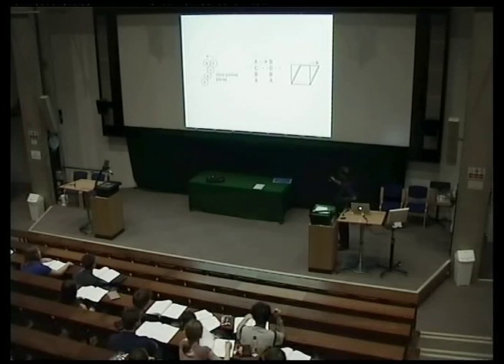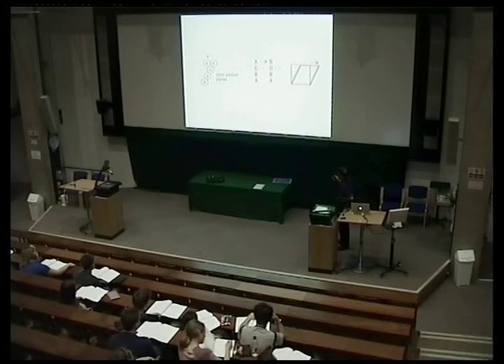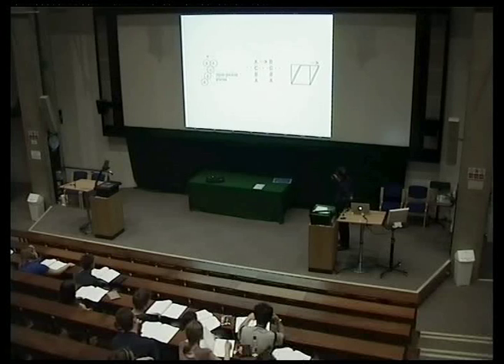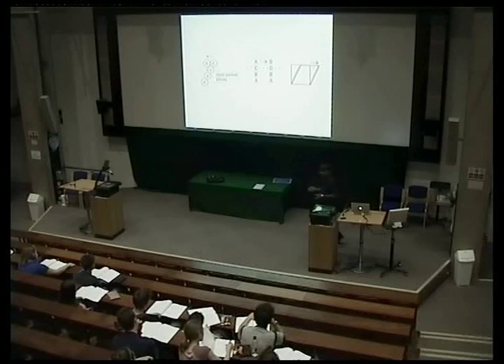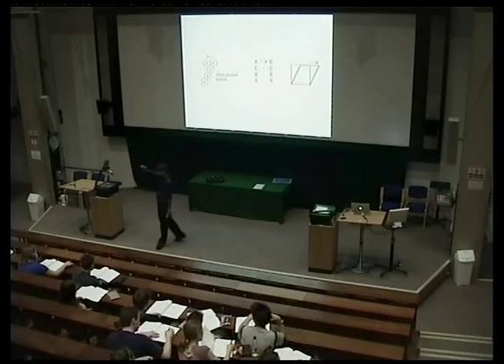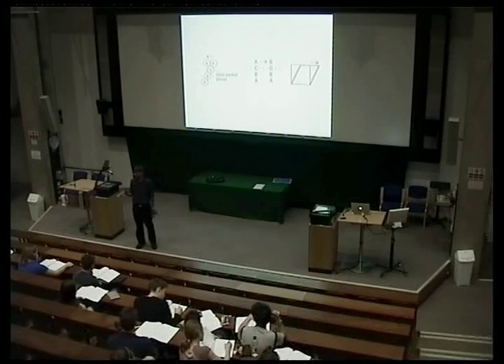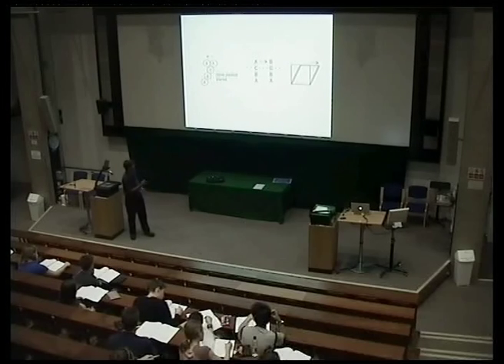Here is our starting configuration with stacking ABC ABC and so on. Then I translate one layer from an A position to a B position, and you can see we've got a different sequence: A, B, C, B, C, B. That layer is a reflection of the layer below about the twin plane. Twinning involves the translation of a close-packed layer — every single close-packed layer — from an A position to a B, or B to C, or C to A. If I do this translation on every single layer, I will create a twin crystal.